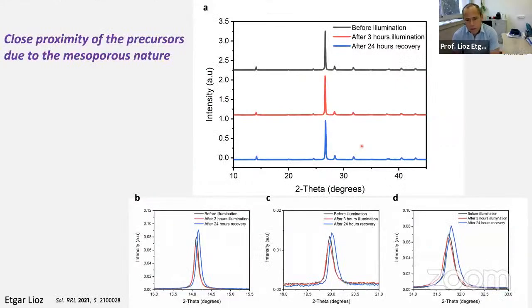We did some XRD measurements following those steps, which means before the illumination, after 3 hours of illumination, and after the recovery. What we found is that the unit cell is changing during that time. What we are assuming is happening is that, since all the precursors are sitting in those mesopore structures in very close proximity, when it degrades, the precursors are separated, that's mainly the lead iodide, the cation, and probably those two.